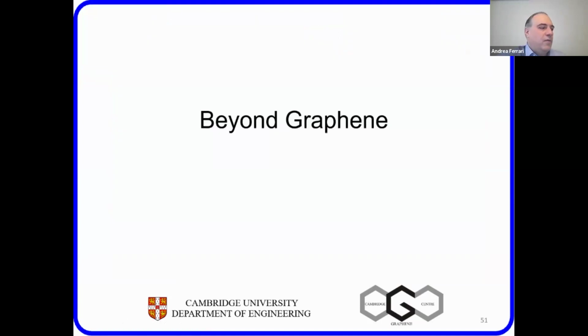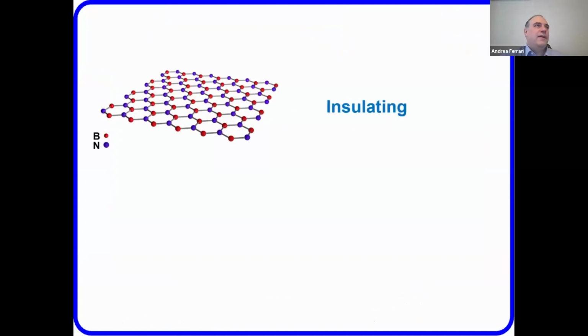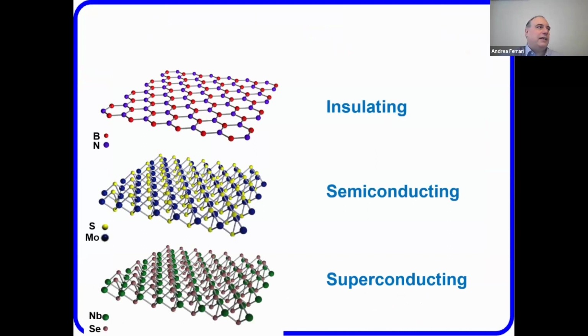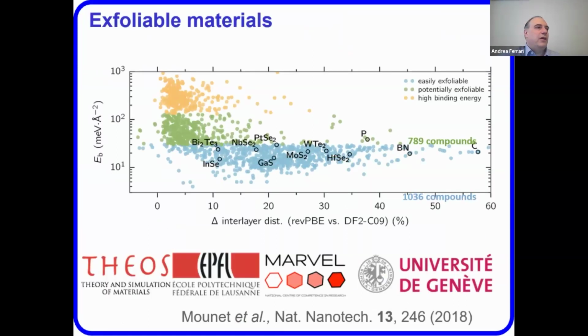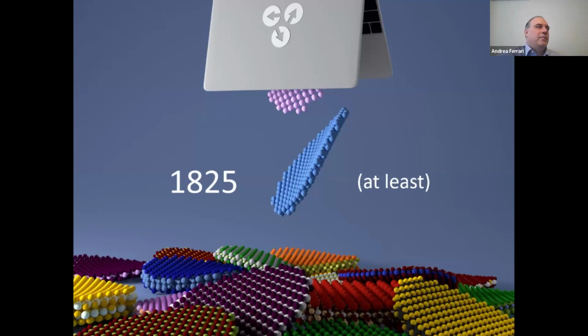Now, graphene is only one layered material, but there are many others. And you know, hBN is, for example, an insulator. MoS2 is a semiconductor. Niobium selenide is a superconductor. So how many of these materials do exist? There was a very nice work done by the group of Nicola Marzari within the Graphene Flagship, where they used density functional theory and other theoretical approaches to look at all the databases of known materials. And long story short, they determined that at least 1,800 materials exist in nature that can be exfoliated. Bear in mind, many works have been published since then, and this estimate varies from 1,800 to 5,000. So we don't know exactly how many, but there are thousands of them.